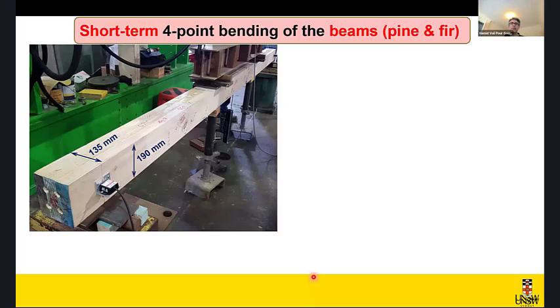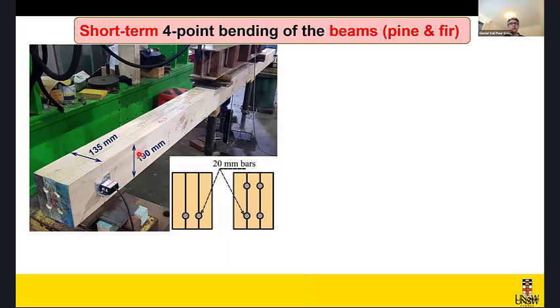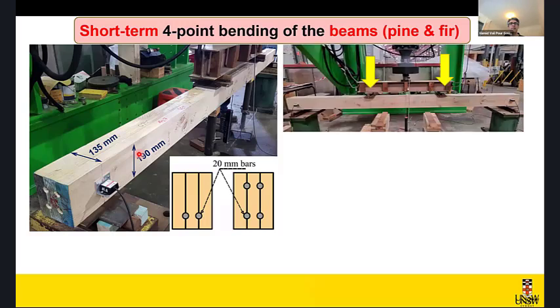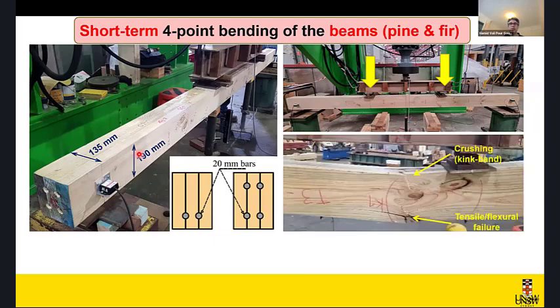So this is an example of a beam subjected to four-point load. The cross-section is 190 by 135, consists of 3 lamellas of pine in this case, MGP10. And then we have some fir also laminated in this case. I believe in total we have tested over 100 beams and over 120 beams and columns, different size and span lengths ranging from, let's say, 1.1 meter in height in the columns up to 6 meter long for the beams.